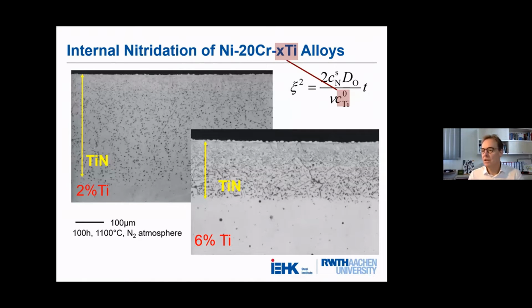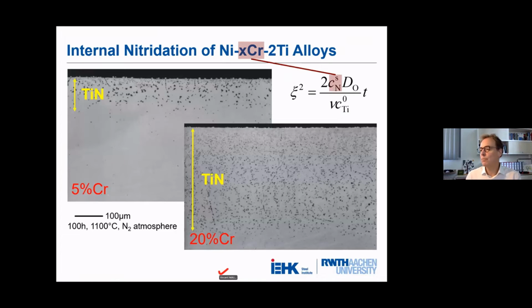This equation describes the internal nitridation of nickel 20 chromium and X titanium. Chromium itself is not nitrided under this condition, but depending on the initial titanium concentration, if the initial titanium concentration increases, then we have a decreasing internal nitridation depth. That is according to this simple equation. If we increase the solubility, that means more nitrogen, then we get a higher internal nitridation depth, as shown here, because adding chromium increases the solubility for nitrogen. Of course, the nitrogen diffusivity also plays a role in this equation.